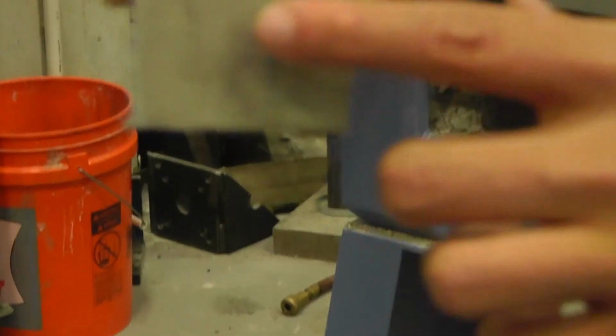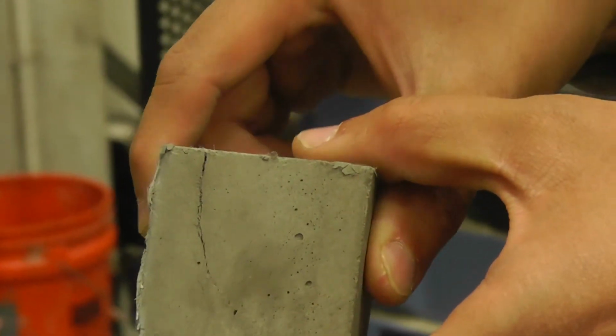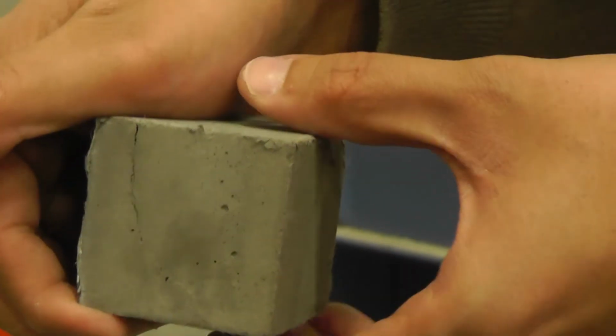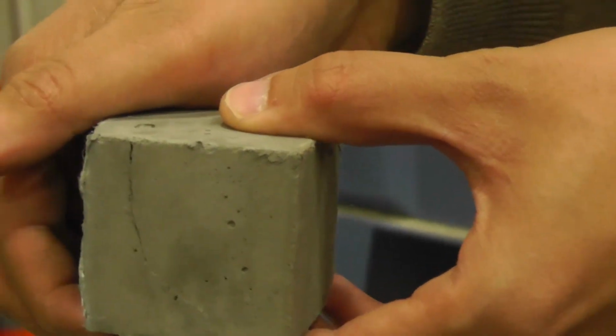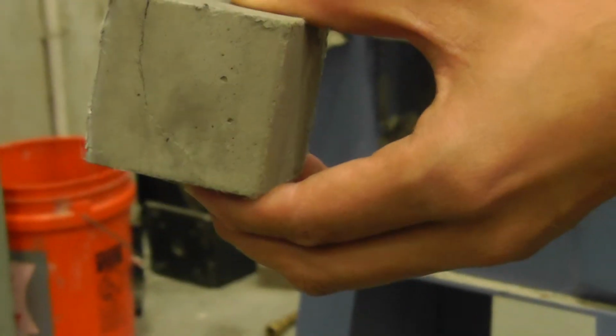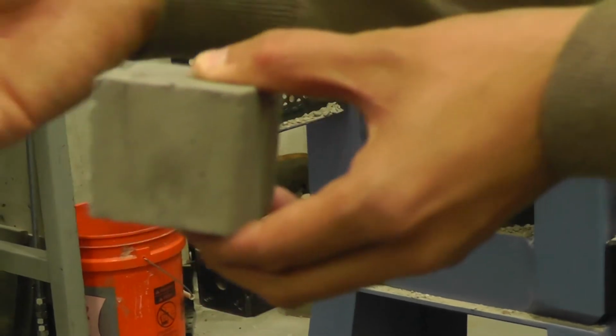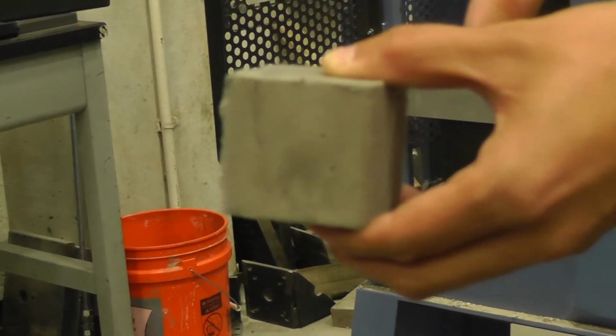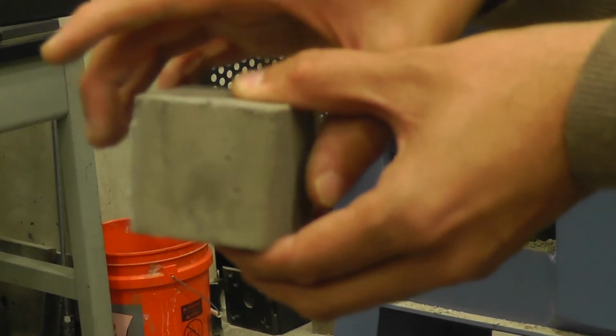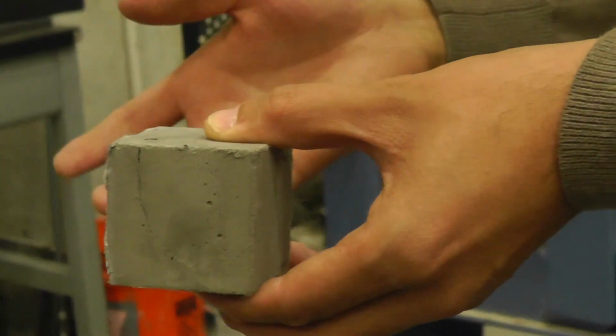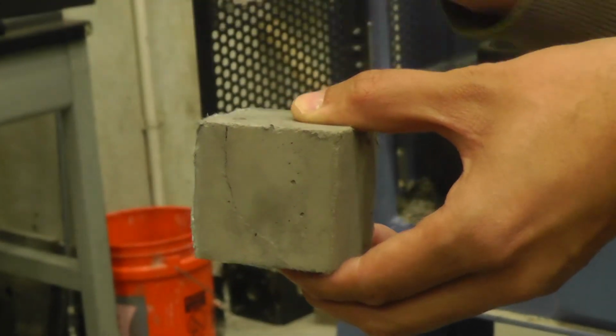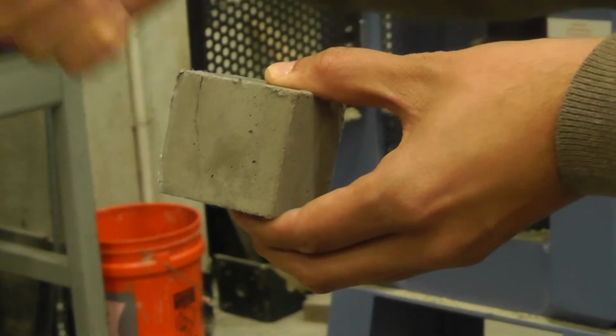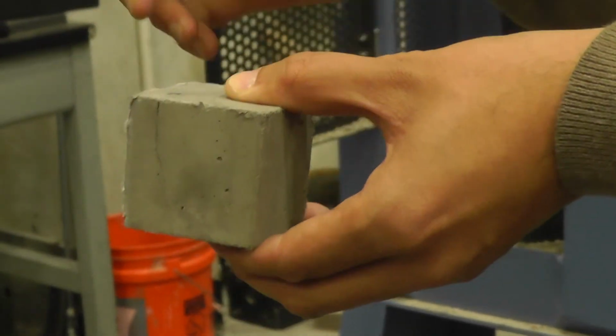So the difference between this and normal concrete is that the final failure will actually depend on the amount of bond between fiber and concrete rather than the compressive strength, because the tensile failure is actually governing the compression failure here, the pulling out of the fibers. If the fibers hold on, it will take a really long time to pull them out.